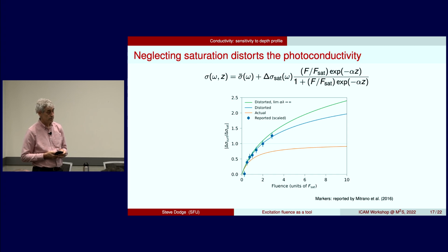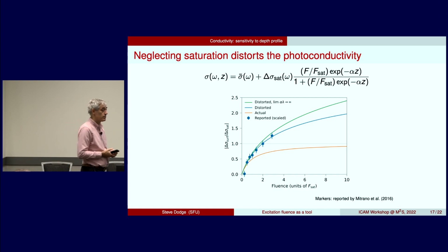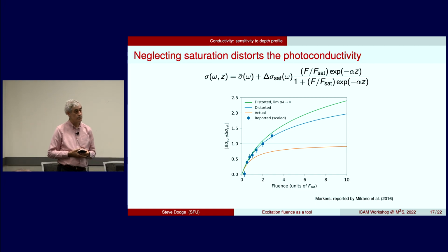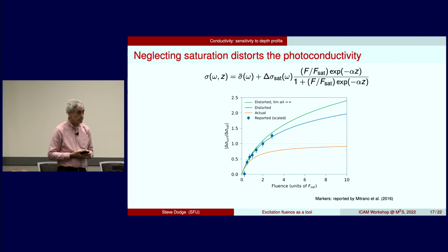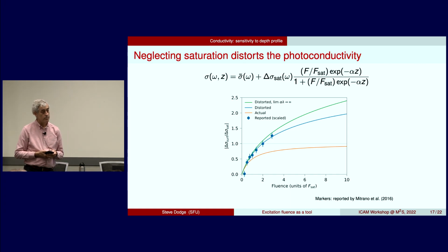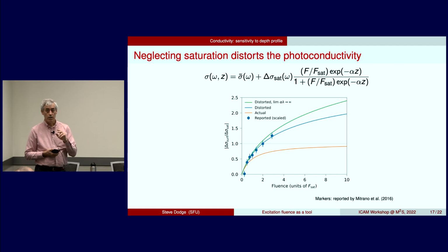But the important point is that if you believe that the interaction is not similar to exciting photocarriers, but has to do with the excitation of a phonon or some low-lying mode, then the extinction depth will be linear in field, and hence the saturation will not happen. Whilst I don't know which one of the two mechanisms it is, it might well be that there's more in this than you are purporting.